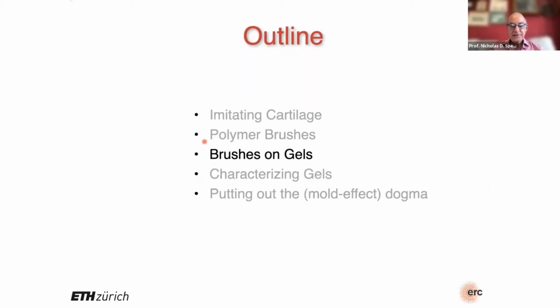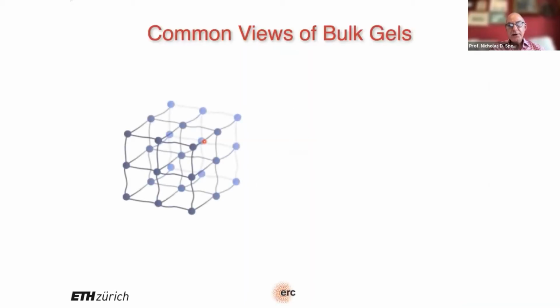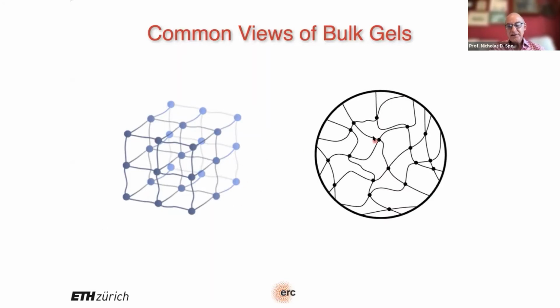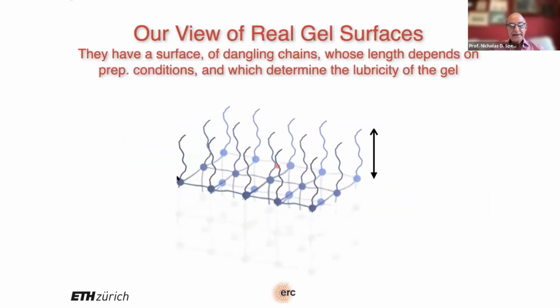Now, brushes on gels. This gets us more in the cartilage direction. And first of all, a word on bulk gels, and this is the work of Yvonne Gombert. In the literature, you see a lot of very diagrammatic illustrations of gels looking almost like sodium chloride, or you get depictions of gels that seem to avoid dealing with the surface at all. What we're interested in is the surface of the gel, and we think what's going on there is that on top of the gel, we have dangling chains. No matter how it's made, it's very unlikely that it's going to be perfectly terminated at the surface without any kind of chains that are not cross-linked. So we believe that all gels to some extent have dangling chains on the surface, and that extent of dangling chains is what leads to the lubricity, the degree of lubricity of the gel.